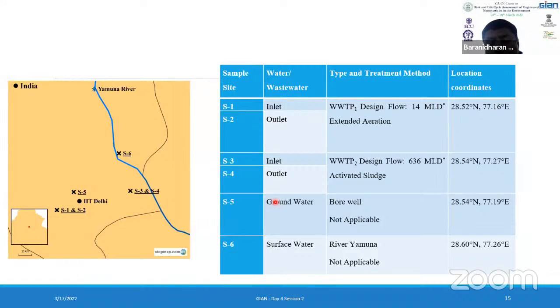But downstream, the sample location for this surface water body was chosen in such a way that it was outside of the city, but still at the outskirts of the city. Most of the industrial units were there in place, and their metal concentrations were very high when looked at in the metal analysis. At the same time, when the surface water sample was looked at under TEM, particle sizes in the range of 200 to 300 were found, and that was also due to the industrial activity that we can say.